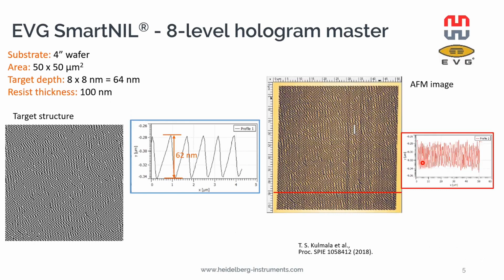We sent them a test structure that was made on a 4-inch silicon wafer, 50 by 50 micrometer area, 8-level holograms, resist thickness 100 nanometers, and the target pattern depth 64 nanometers.